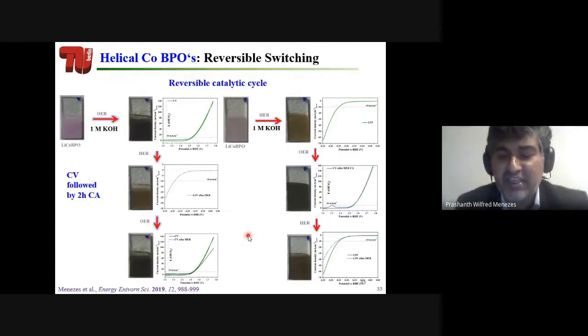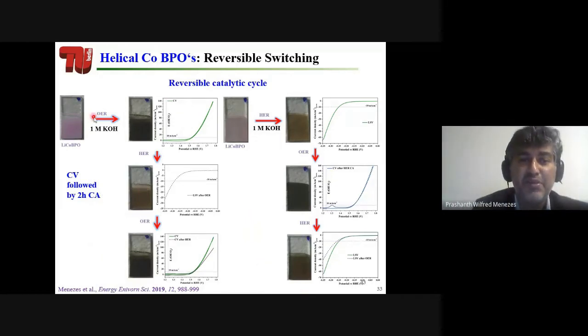So one of the interesting aspect of this work is the reversible switchability. That means you have this film, you apply oxygen evolution reaction, and you change your catalyst. That means your catalyst is no longer the same catalyst after you apply your potential. That means it's a pre-catalyst. And then if you apply the reverse, that is hydrogen evolution reaction potential, you are getting some light brown colored film. And then if you apply again positive potential or oxygen evolution potential, then you are again getting the same black colored film. So that means if you look at this way, you form this catalyst, and then you can reversibly form this catalyst every time when you use it without losing any activity.